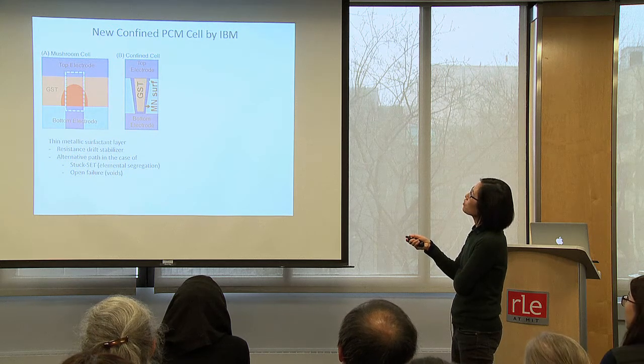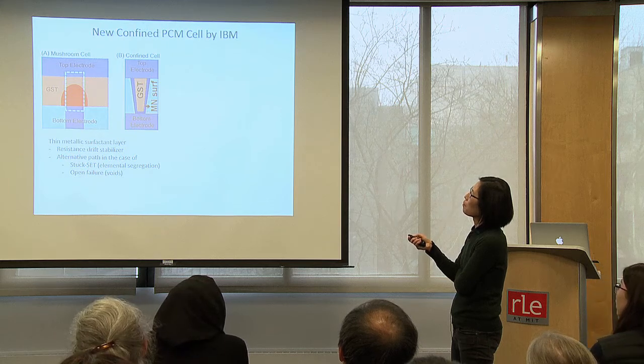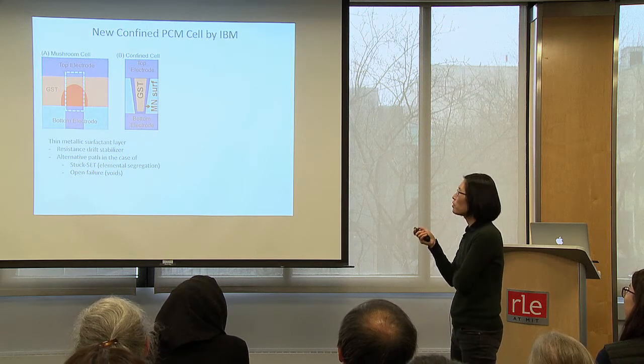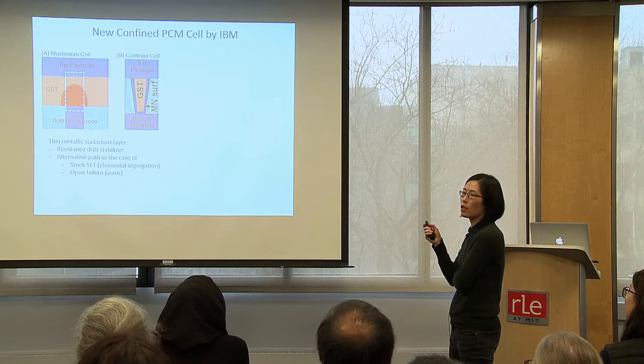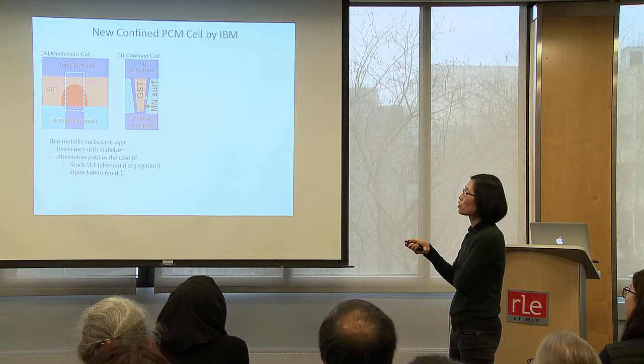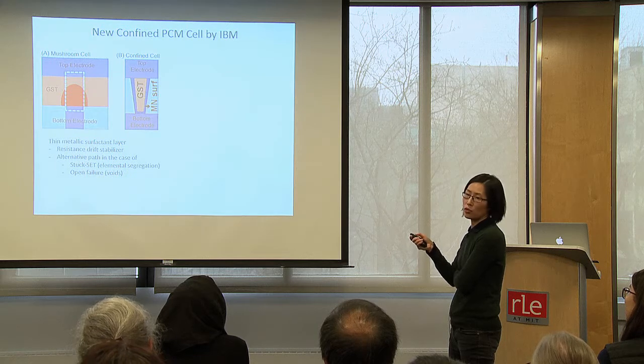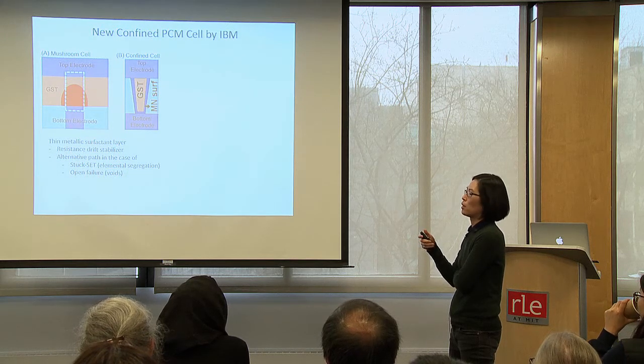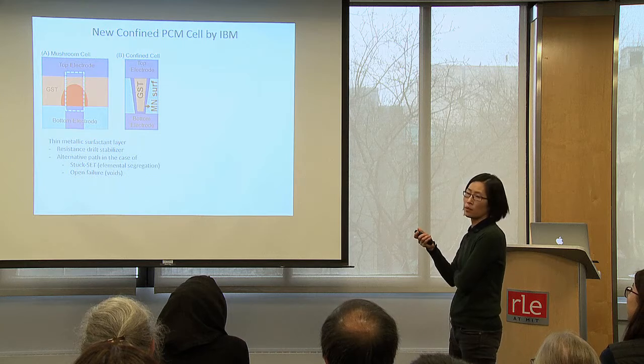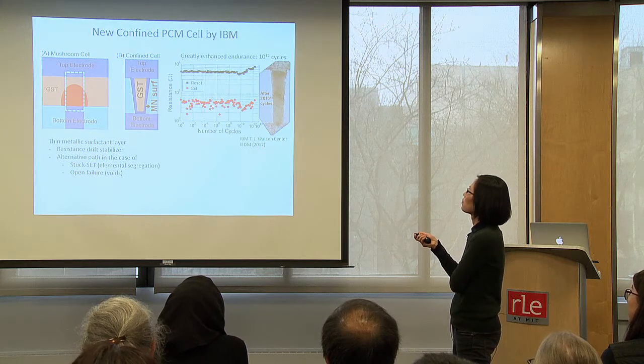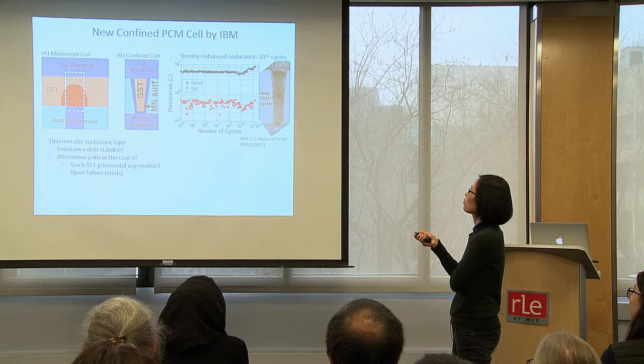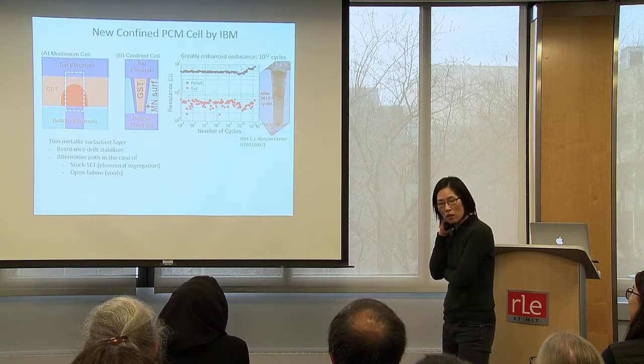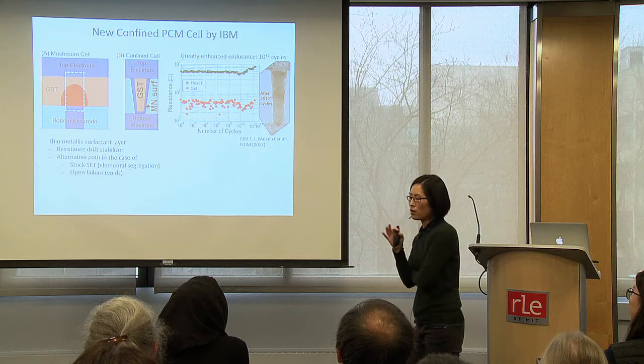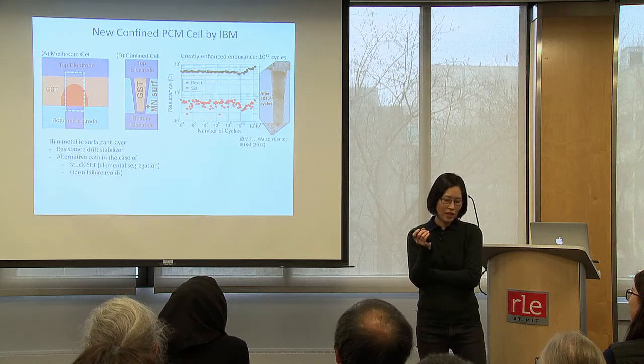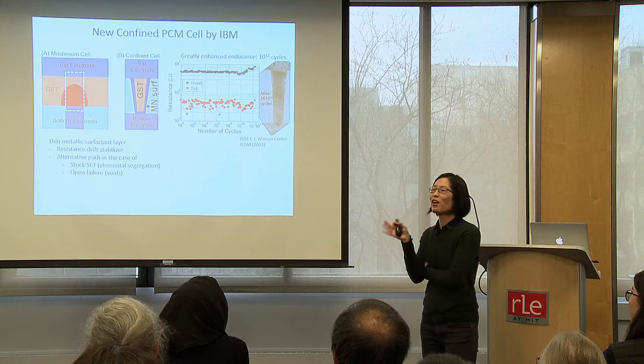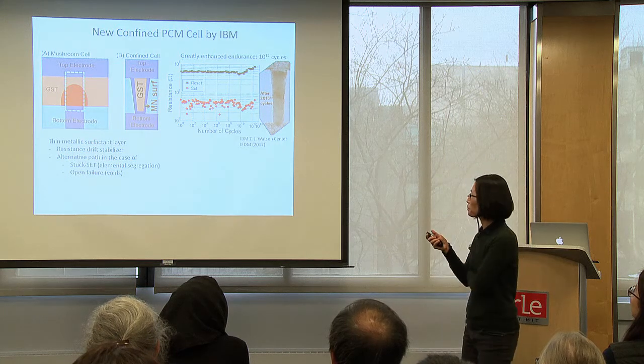And the novelty is that it's surrounded by a metallic surfactant layer. The idea of this layer is that even if you create a void, you still have a path for the current in the presence of a large void, and it could perhaps prolong the cycle numbers. And in fact, last year, they showed a record number of 2 times 10 to the 12 cycles, which was quite an achievement. The device did not fail; the engineer just stopped the test.